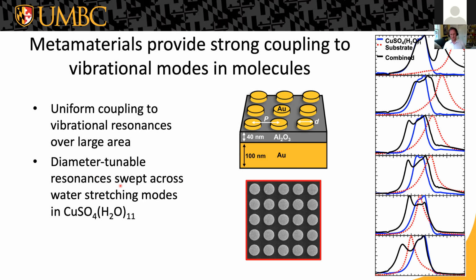In this case, again, collective coupling to the vibrational modes of that material, and specifically here to the symmetric and anti-symmetric stretching modes of the water in this hydrated copper sulfate. And again, the resonance frequency can be tuned by changing the diameter of these disks. So you can sweep the plasmon resonance frequency across the vibrational mode frequencies inside this material. And as we do that, we see a splitting of the transmission spectrum or the absorption spectrum as the